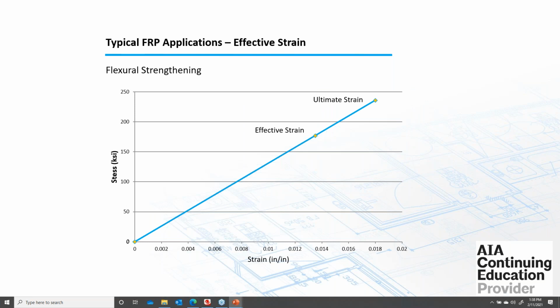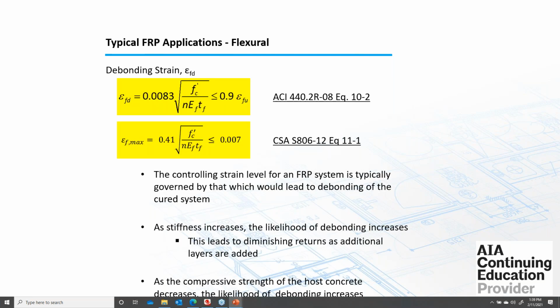Now, as far as that 70%, why is there a limit? Why can't we just continue to put more material on and get more strength? The reason, and I mentioned this before, is that we can't ever get to the ultimate strain or stress of the material. It's going to delaminate at some point prior to that. So the guidelines have come up with this debonding strain, or effective strain, that gets calculated based on these equations here. They're the same in CSA and ACI. The only difference is between the metric units and the US customary units.